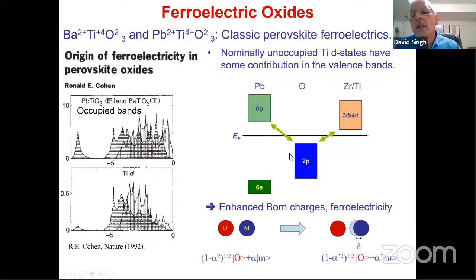And of course, the amount of covalency depends on the distance between the atoms. And so if you change the distance between the atoms, you change the amount of covalency. But what is covalency? Covalency is a mixture of these states, right? So it means that even though the lead 6p state is in principle not occupied because it's a cation, there is some hybridization, some mixture. And so there is some charge on this 6p state, and that amount of charge depends on the distances between the atoms.